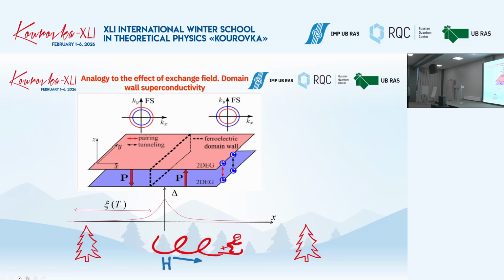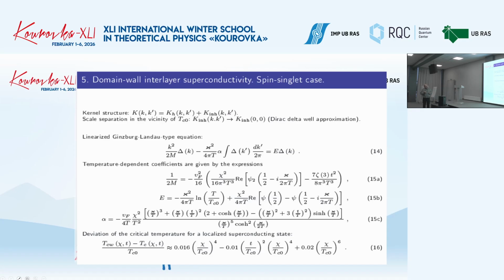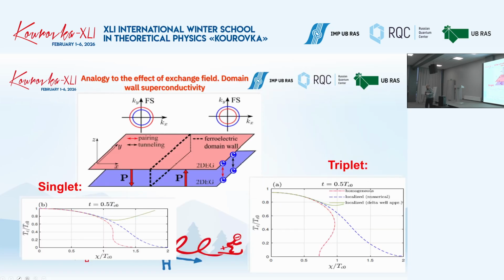Just because this band shift changes sign, it's much better for Cooper pairs to be localized near this domain wall. And this is a sort of schematic behavior of the order parameter. It's a sort of exponential behavior, at least close to the critical temperature. And the radius of localization should be a sort of coherence length. And we solved some self-consistency equations, which in this case should be integral. And these are the plots.